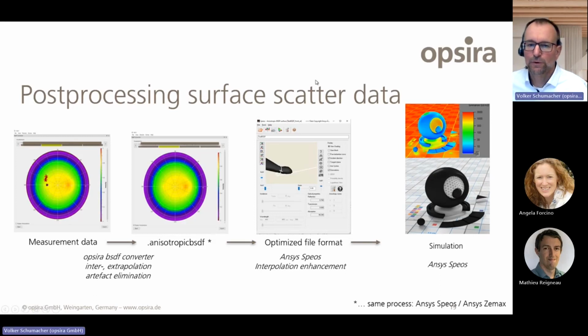Some words on post-processing of surface scattered data. We have on the left side the measured data from the goniometer. We see some artifacts in here. For example, there will be some shading of the light source, which we will see here and there. And also we have some very high scattered angles at the high angles, which will be shaded by the machine itself. And we handle this via the Opsira BRDF converter.